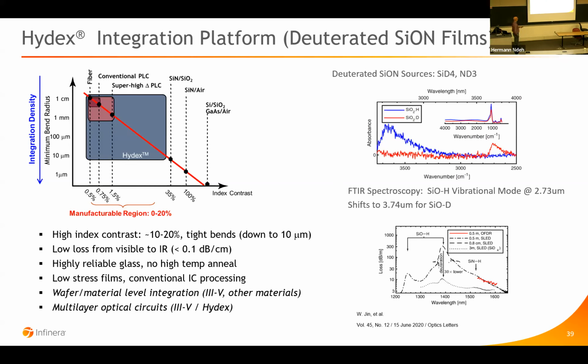What's nice about using the deuterated sources is you can use them with PECVD. So that drops the deposition temperature down to 250 to 400 degrees C. And now I have a low hydrogen content process that I can put into the process of my device. I still have to worry about my hydrogen budget, so I have to worry about what other processes I put in so they don't add hydrogen back into the film. But I can make very low hydrogen content films and use those for waveguides in my device and integrate them right into the chip.